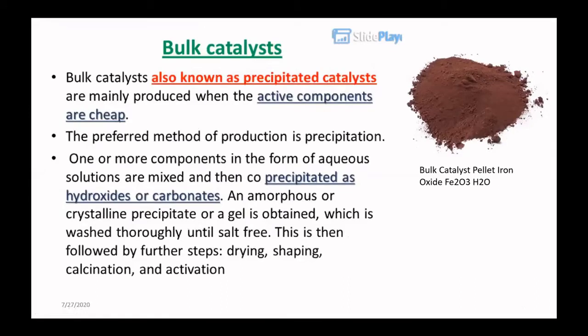For bulk catalyst, especially for cheap materials where the active components are cheap, for example ferric oxide, the catalyst is made through the precipitation method. And the materials are not dispersed on a matrix. So we use these materials without dispersing them into a matrix, for example ferric oxide.